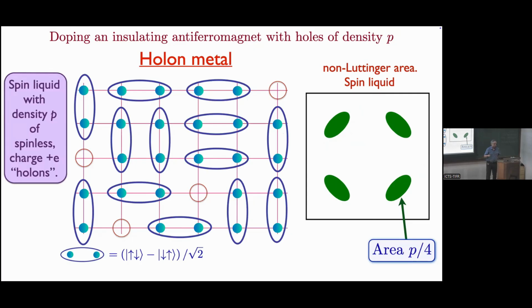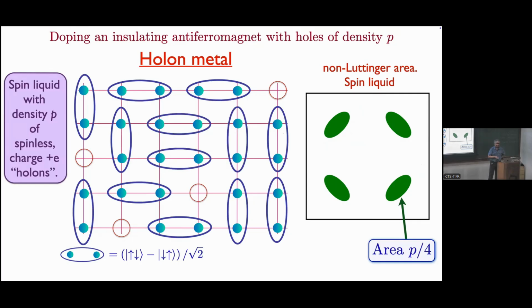Okay, what about more exotic spin liquid states? The earliest type of states that people talked about are called a holon metal, where you've got resonating valence bonds, but you've also got these vacancies, which are called holons, which can also move around, and which don't carry any spin. In this complicated state, you don't know what the statistics of these holons are, but in many models they're fermions, and if they're fermions, they have to form a Fermi surface in any metallic state. So again, by just simple geometric arguments, you can predict the size of the Fermi surface, independent of all the details of your state.